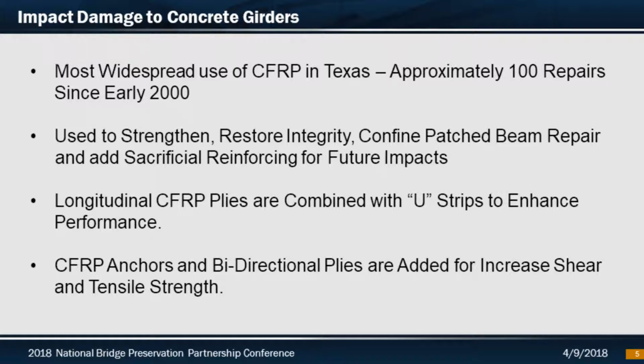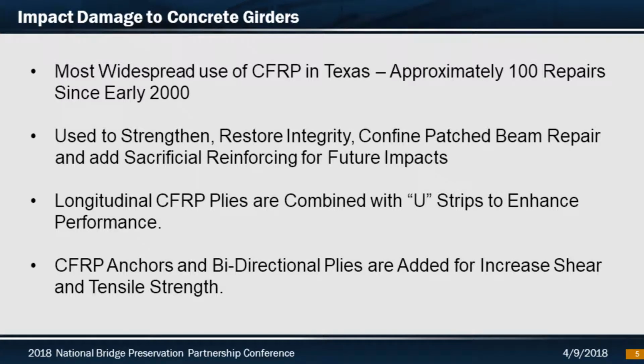We probably have had approximately 100 repairs since 2000. As was mentioned, it's used to strengthen, restore the integrity, confine the patched beam repair, and add sacrificial reinforcing for future impacts. That's kind of been noticed over time after we've made some of these repairs. We're using a longitudinal CFRP on the bottom flange of the beam combined with U-wrap strips, which help enhance the performance and bonding. We've also started getting into CFRP anchors with bidirectional plies added for increased shear and tensile strength.